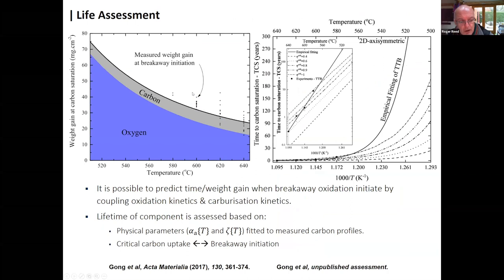Of course, interesting scientific observations are made. So you can see here we were able to rationalize the fraction of the mass gain which is due to oxygen, so due to the oxidation reaction, and then also the carburization. Of course, you can see here that actually with temperature, the amount of weight gain due to carbon is approximately constant, consistent with our reservoir effect.